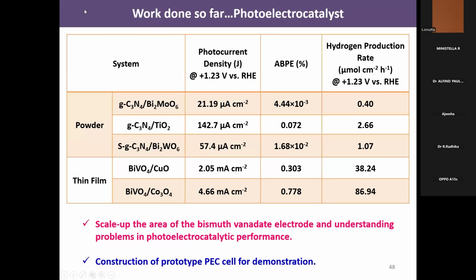So we have done several works with the powder photoelectrocatalyst, especially the powder-based system produced through the hydrothermal method. Then the thin film approach for making the device. We have compared the performance for the hydrogen production rate and the efficiency of the system. In the powder processed method, it shows poor hydrogen production rate and poor efficiency. But once we make it in thin film form, it shows a high hydrogen production rate. So we have taken this thin film approach for making the prototype device.